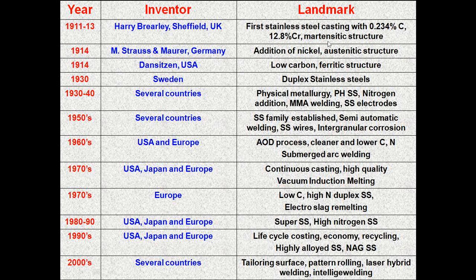Today we have mastered the technology of stainless steel to produce from a normal conventional stainless steel to a highly alloyed, highly clean steel with tailored properties for various applications. You can see nickel and austenite structure, low carbon ferritic structure, then duplex stainless steels, understanding more on the physical metallurgy, then welding and other technologies. Then they found this problem of sensitization and intergranular corrosion. Then with respect to the technology for manufacturing using the AOD process, cleaner and lower carbon, nitrogen containing and submerged arc welding, continuous casting, vacuum induction melting, electroslag remelting.